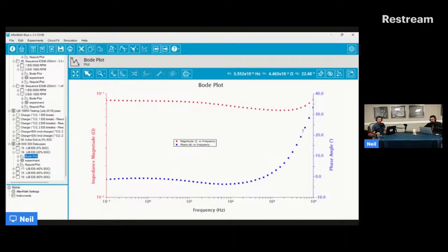If the program picks a high frequency, like 20,000, 30, 50, 80,000 or 8,000 hertz, you could end up in a similarly odd situation. Now you have a positive phase angle because it's inductive behavior, and if it takes the Z imaginary, it might end up as a negative number. So part of the issue is that some automatic program just assumes this frequency is where it is, and then which impedance parameter it is taking. You can see two instances I've shown you where that number might happen to be negative. So those are a couple ways where you might end up incidentally with what appears to be a negative solution resistance.